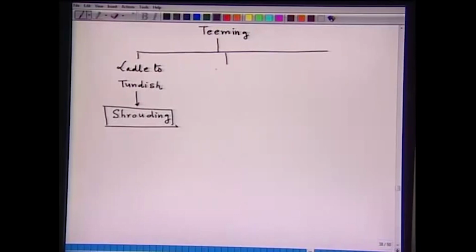Then molten steel is contained in the tundish, because during the transfer from ladle to casting, for example, in continuous casting, tundish is the last refractory lined reactor where molten steel is in contact with the refractory material. So, accordingly the tundish can also contribute to a large number of inclusions if proper control is not being done. What is the proper control?